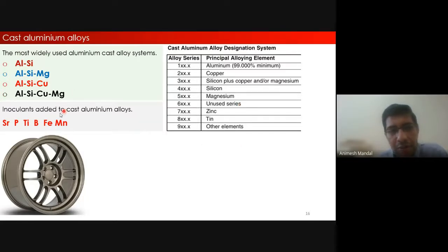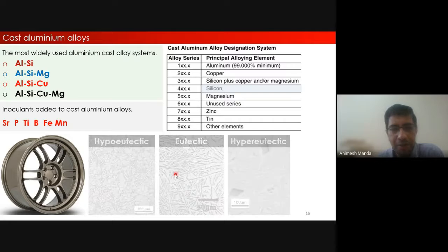Apart from these alloying elements, there are some elements which are added in very, very trace amounts. These are called inoculants. It could be strontium, phosphorus, titanium, boron, iron, and manganese. These are added to these particular alloys to impart certain properties, mostly strength, but there are other properties as well, in some cases to improve the ductility. These elements are frequently added in different ratios so that you can improve these properties.